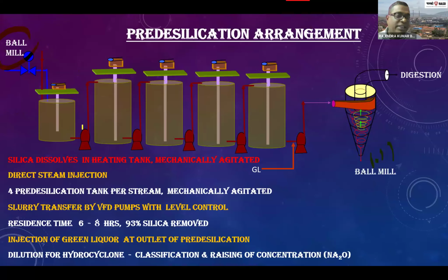In the pre-desilication area, we have received the output of the ball mill, that is minus 63 micron size. Then we are injecting steam, direct injection. In the first stream I have four desilication tanks, and residence time is 6 to 8 hours. 93% silica is removed at this stage. Injection of green liquor at the outlet of the pre-desilication area. Spent liquor is injected here, and green liquor we are injecting here.